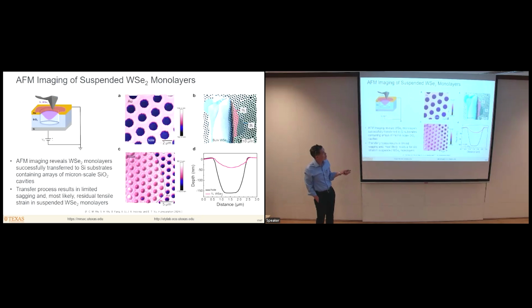This shows an AFM image of a region of the holes that are covered by the tungsten diselenide, and then some holes over here that are uncovered. And by looking at line profiles of each of these, we can see that indeed the tungsten diselenide monolayer bends over the hole, and there's a little bit of sagging that occurs because of the way the layers are transferred.